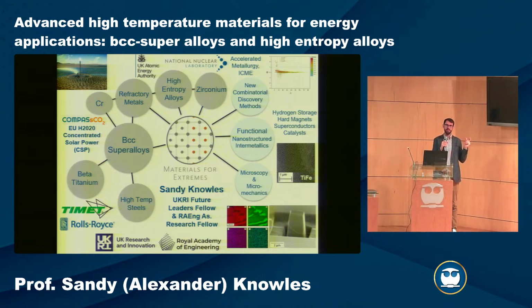But in nickel-based superalloys, we also want dislocations that become harder to move when you go to high temperature. So you have this idea of anomalous yield behavior. It happens in the ordered intermetallics because as you change temperature, you change the energetics of dislocations and cross-slip. So potentially you can have a trapping mechanism. Ideally you want a material that is ductile and allows dislocations at low temperature, but becomes harder as you go to higher temperature. There are ideas we try to use to design around this, but it's quite complicated. Yes. Thank you. Some other question?